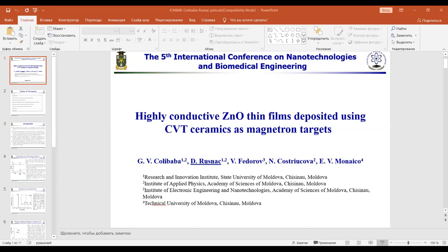The classical sintering method of ceramics have many disadvantages, including the extremely high sintering temperatures of about 1,300 to 1,500 degrees Celsius. Recently, the chemical vapor transport CVT technique was proposed as an alternative method for sintering ceramics.